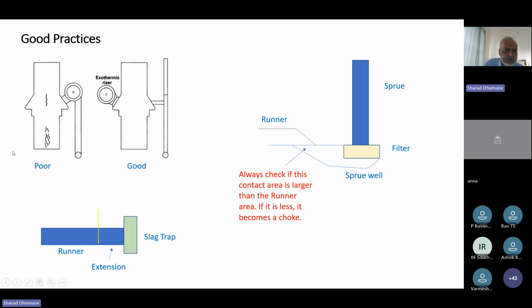Good practices. So this is a poor practice. Why is this poor practice? Because we have attached a runner to the riser. This makes the riser a hot riser. Traditionally, this is called a hot riser. But why is this poor design? Because in many cases the riser neck is designed for a cold riser, and when you add a runner to the riser, it increases the time the riser remains in liquid state. When the riser remains in liquid state for longer, it also affects your riser neck. The riser neck, which you had calculated as 0.6 times casting modulus or 0.7 times casting modulus, then changes, because now we have made the riser hot by adding a runner to it.